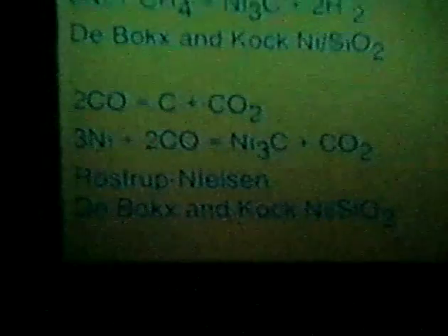Now you can say this is an endothermic reaction. There may be some effect of that. We did it here for an exothermic reaction, and again you find there is an equilibrium with the carbide, and there is no equilibrium with the graphite over here. We have agreeing results of Rostrup-Nielsen and our own data. So that indicates that first of all you are getting the carbide, but the carbide may decompose to carbon and the metal. I think that's a very important item.